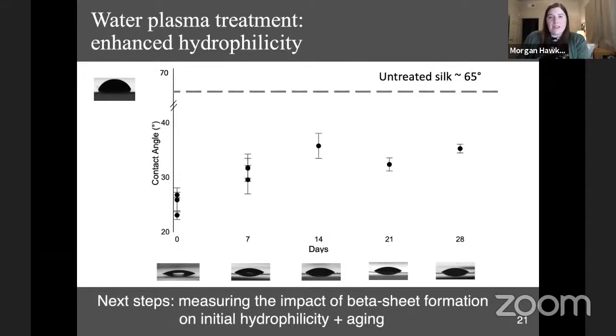So a lot of our silk materials have been sitting around for several months due to the lab shutting down from COVID-19, and that's really inspired us to look closely at the impact that aging our silk films has on their cross-linking and what's called beta sheet formation, which is an irreversible crystallization of the silk film. And we think that this beta sheet formation is likely related to, or has an impact on, the film's hydrophobic recovery rate, as well as how it responds to the plasma. So I'm very excited about these experiments that are currently underway to explore this further.